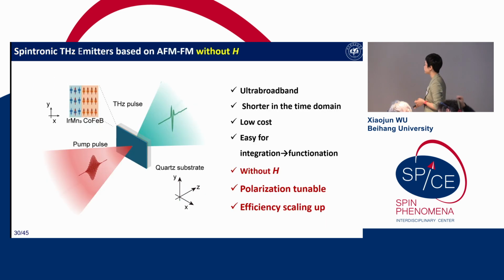So, our small conclusion for this one is that we have demonstrated a spintronic terahertz emitter based on antiferromagnetic and ferromagnetic heterostructures, but without an external magnetic field. We see the potential application is that we can use this for 4-inch or even 8-inch wafers without magnetic fields, for single-shot imaging. We do not need to scan, just use the photoconductive antenna, and it may also have the chance to produce very strong field terahertz for extreme terahertz science and applications in the future.